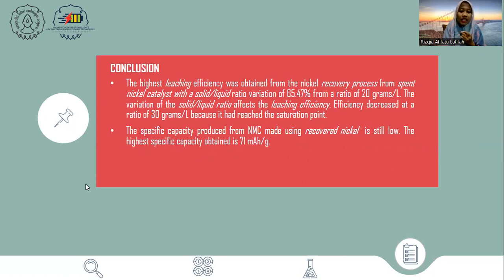And the second is that the specific capacity produced from nickel manganese cobalt made using recovered nickel is still low. The highest specific capacity obtained is 71 mAh/g.